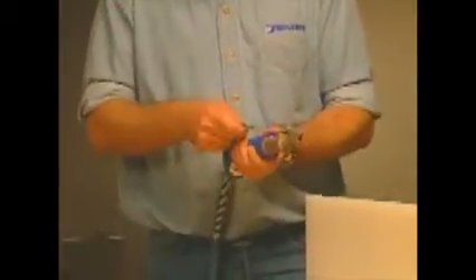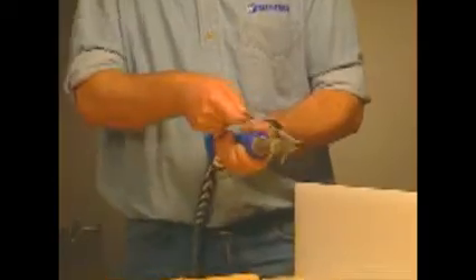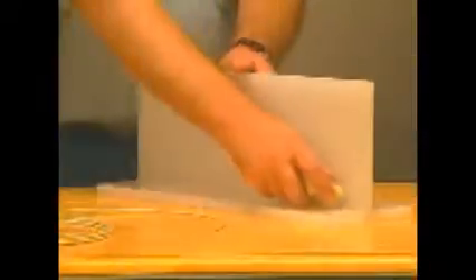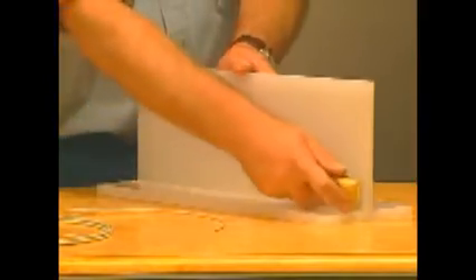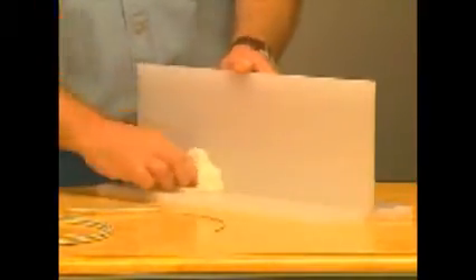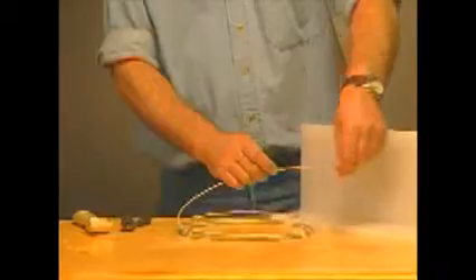Check the welding rod chamber of the high-speed tip for impurities. If necessary, clean with the tip cleaning brush. Scrape the tack weld to eliminate any oxidation caused by the tacking process. You are now ready to weld.